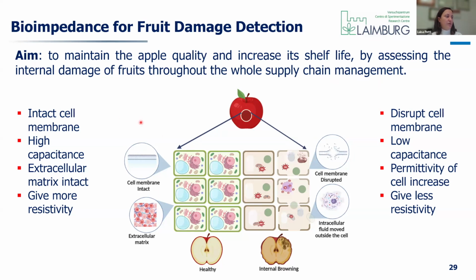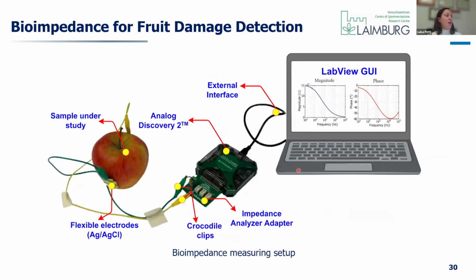Of course, we want to have something healthy, which has an intact cell membrane, a high capacitance, an intact extracellular matrix, instead of something with internal browning, which you typically recognize only by destroying the apple, because it's something you don't see. Typically, you don't see much, at least when it starts from the inside, where the membrane is disrupted, and you have different behaviors, different water content as well, and also different conductivity.